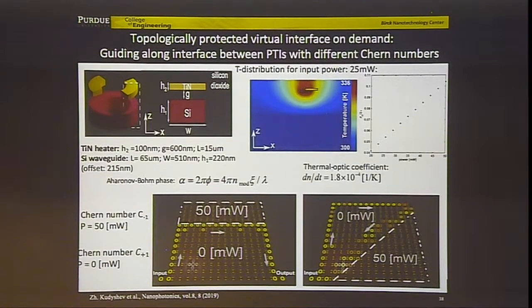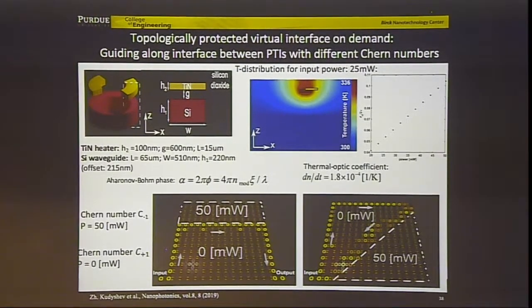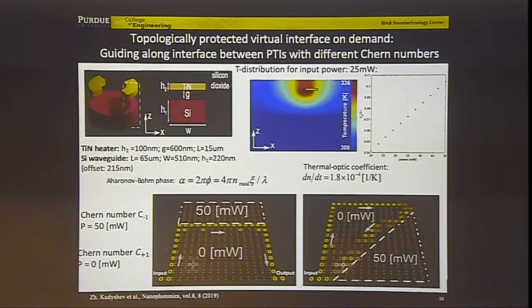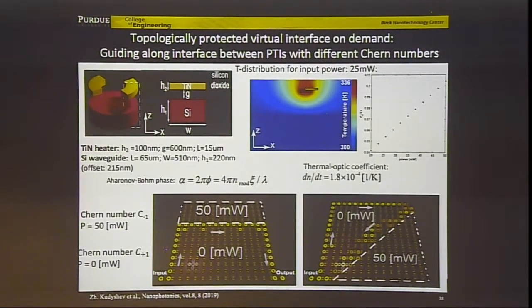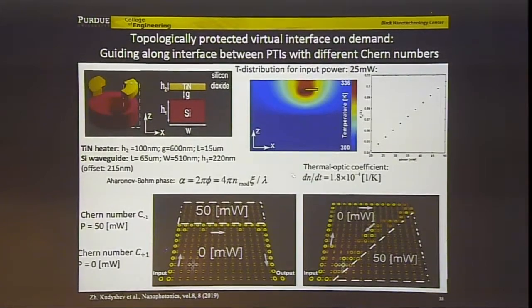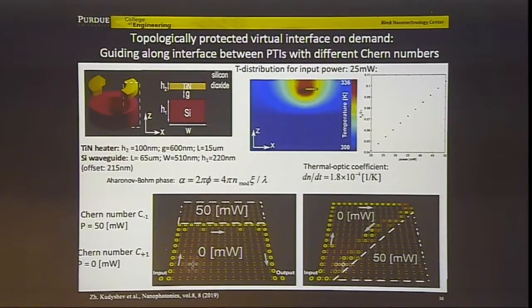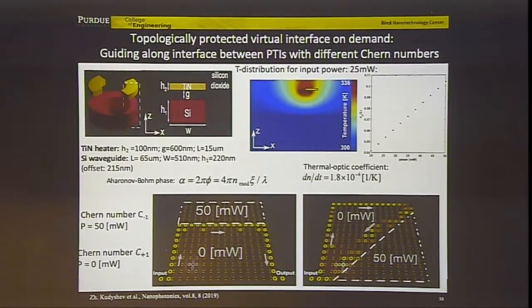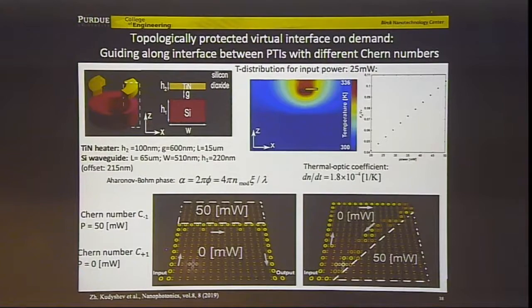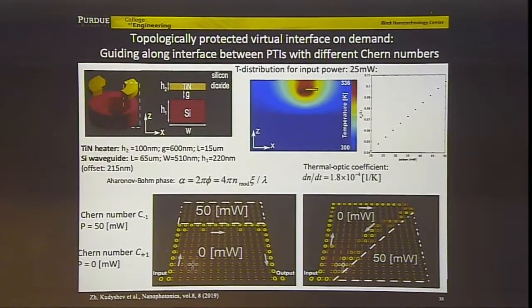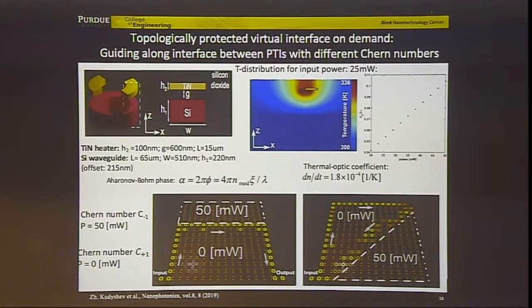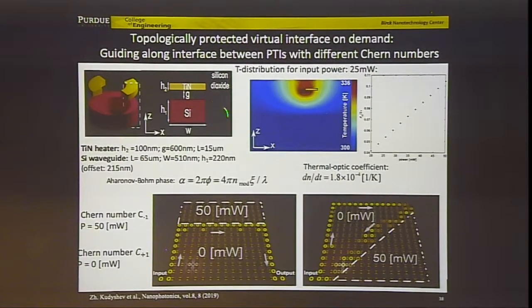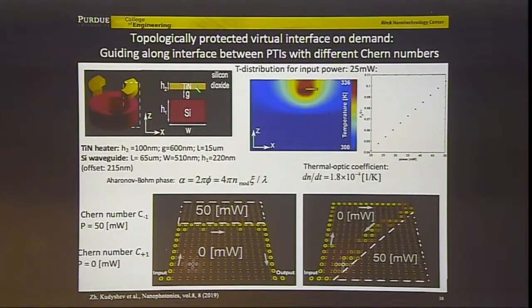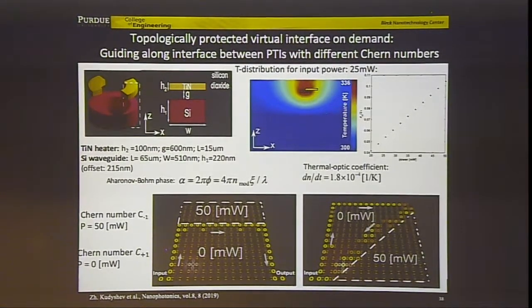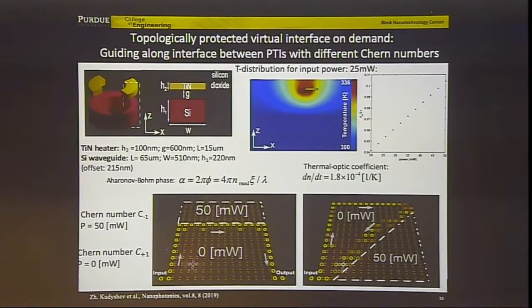And how could you actually switch this synthetic magnetic field? By changing the refractive index. The simplest way, if you speak of silicon, we know that in silicon there is a very strong thermo-optical effect. So we change the temperature, we change the refractive index. The refractive index depends on the temperature, and because of that, the Aharonov-Bohm phase would depend on the temperature, to the extent I could switch the Chern number from +1 to -1. So we just combine this silicon waveguide with these titanium nitride heaters. And titanium nitride is stable, which can sustain high temperatures.